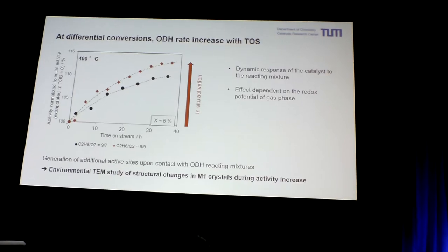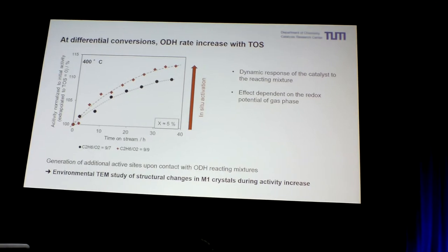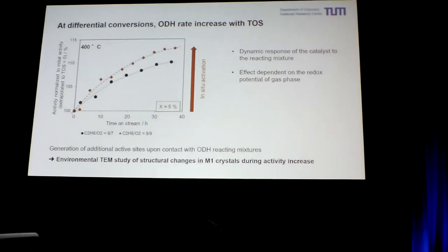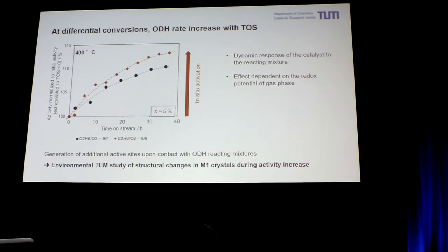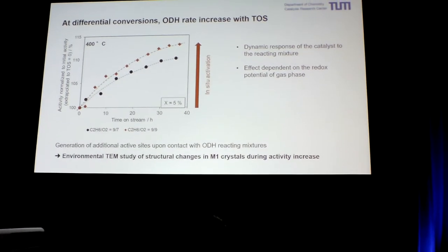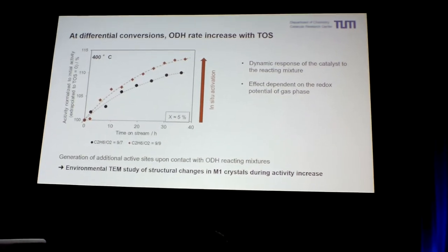So we wanted to understand this effect of the tellurium before showing you what we think is the reason for this promoting effect. A little bit more, we have another observation of these catalysts when we studied them under differential conditions, so with conversions about 5%: we observed that there is an in situ activation in the first hours of time on stream. We also observed that the extent of this in situ activation changes with the gas composition.